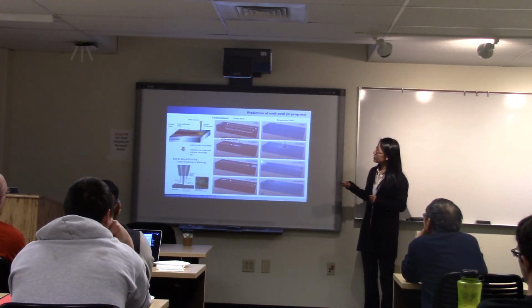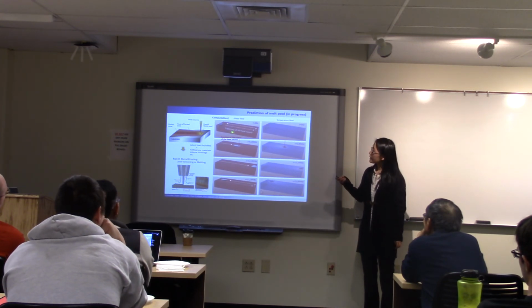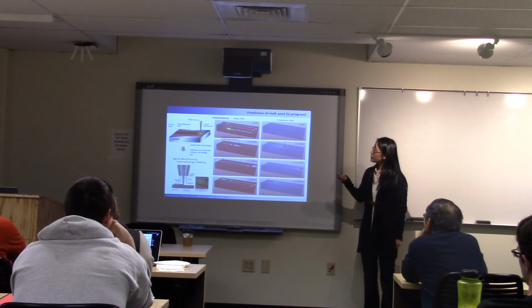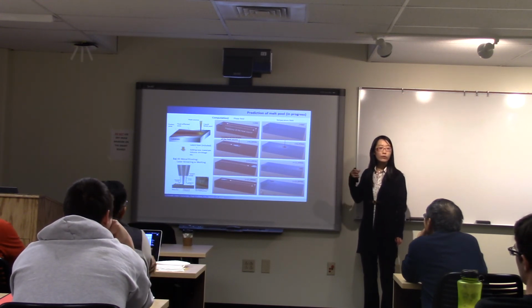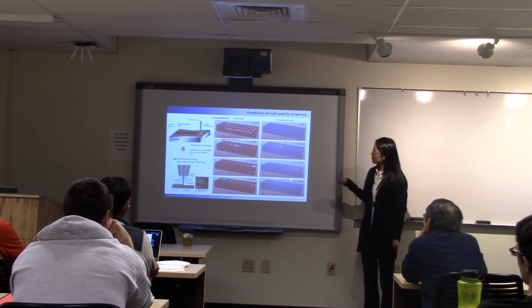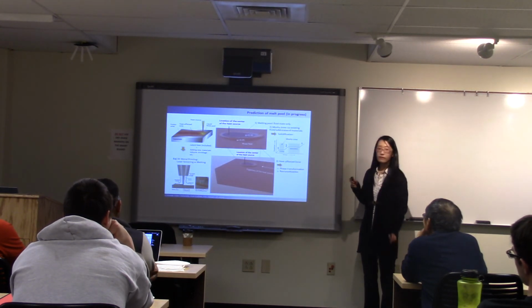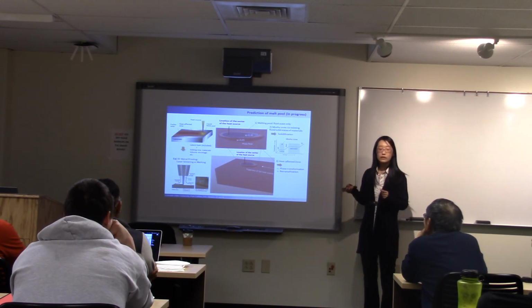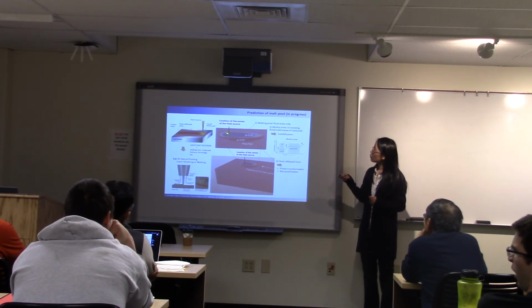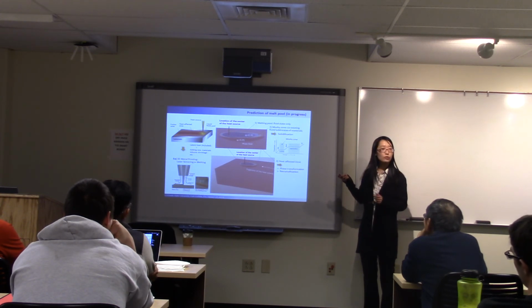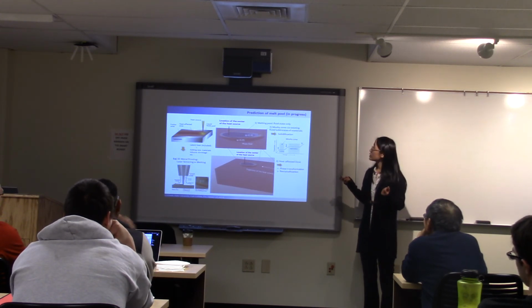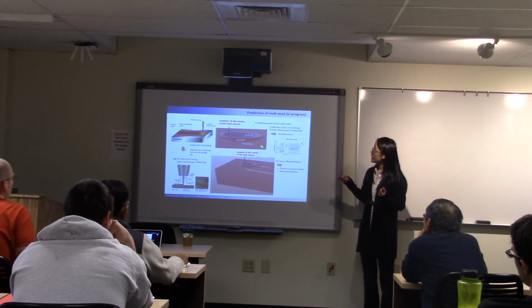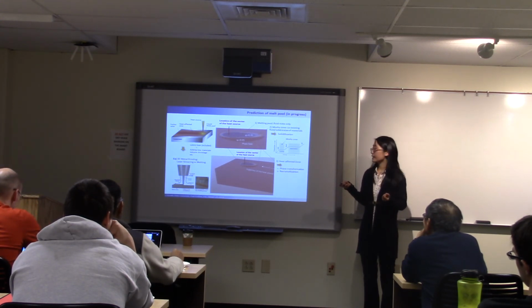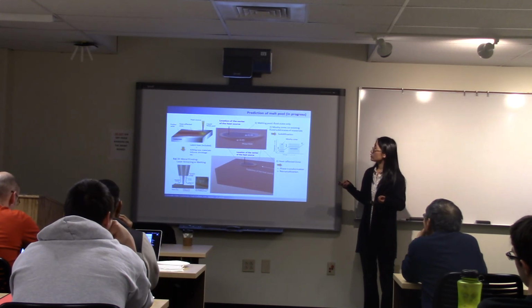So here are some of our results on the prediction of the melting pool, and we can see the melting pool geometry and its movement with the laser scan, as well as the temperature field. We can also have a very detailed picture of this melting pool from this prediction, consisting of the fluid state, the mushy zone, which is coexistent fluid-solid states, as well as the heat affected zone, where the phase transformation and recrystallization could possibly happen.